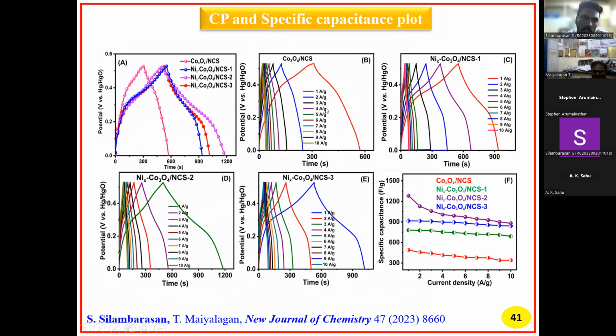Next one, the charge and discharge with the specific capacitance plot. So here figure A is the cobalt oxide with nitrogen doped carbon, sample 1, sample 2 and sample 3. For charge and discharge we measured here up to only 1 amp. So when compared, sample 2 has the longer discharge, so it gives more performance.